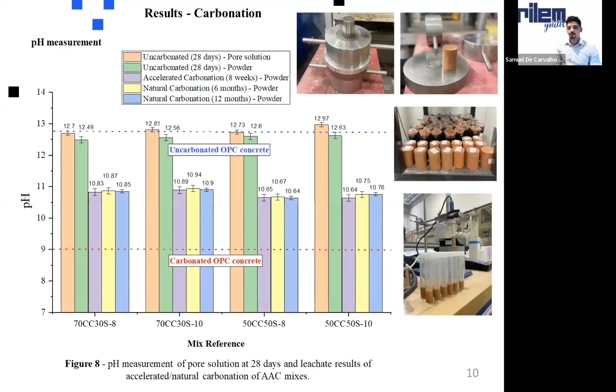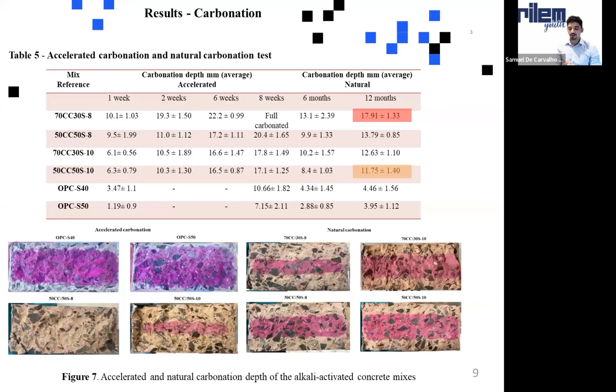So the main question about this high carbonation was, as you already knew, previous research already showed that geopolymer and alkali-activated materials have this really high carbonation depth. But recently, some studies, a topic of so many studies, showed that this carbonation most of the time was not due to the pore solution or the different microstructure of the geopolymer concrete. In this case, most of the studies were showing that the phenolphthalein test, this particular phenolphthalein test, always overestimates the carbonation.